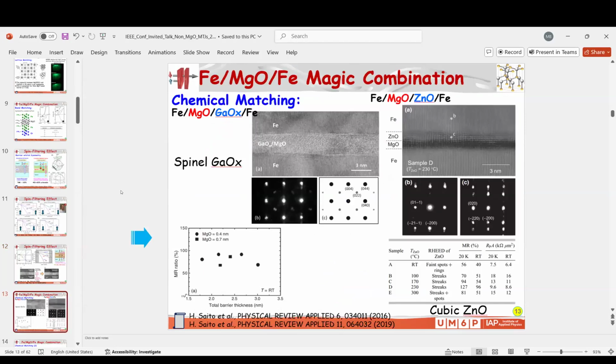Many researchers try to use other barriers, for example, gallium oxide, which is a spinel, or zinc oxide in terms of cubic. But the problem here, which is a good aspect of MgO, is the surface energy. The surface energy is compatible with iron. If you want to try another oxide, you need a seed layer. And this is also inconvenient for using the other ones. People just strive here to realize this barrier.